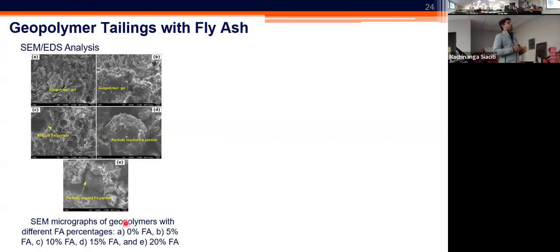In this case, we were able to look into the SEM micrographs and visually confirm that 15% was the ideal optimum range because it still allowed for geopolymerization of the fly ash, but in the case of the 20%, we had some amount of the fly ash that was present in the original inert form and did not really participate. For those of you who are familiar with scanning electron images, fly ash is a very distinctly visible material. If you put the fly ash powders under the microscope, you recognize them by these beautiful spherical particles. So this is a distinctive feature of the fly ash that was also visible from our images.